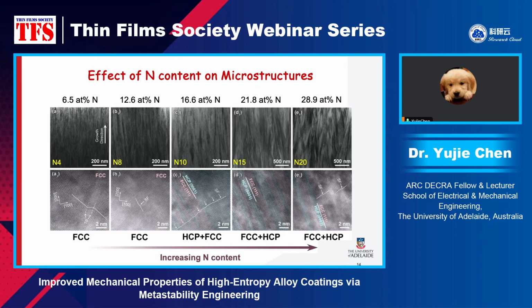As we mentioned in a previous slide, interstitial elements can affect the phase stability. Indeed, the high resolution STEM images here show the phase structure, and it shows that the nitrogen content has a strong effect on the phase stability and stacking fault energy of the high entropy alloy here. As we can see, it forms an FCC structure when the nitrogen content is relatively low. It's a single FCC phase. As we increase the nitrogen content, at a higher nitrogen content, they form a dual phase structure, both FCC and HCP, right? It's like a nano-layered FCC and HCP. The volume fraction of these 2 phases changes with the nitrogen content.